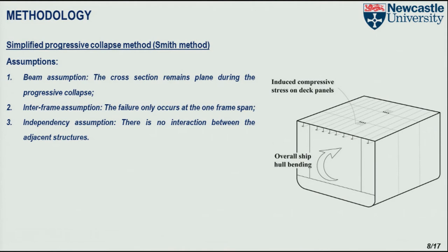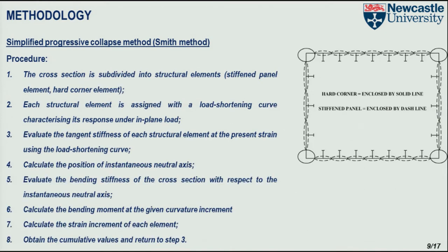Step one and step two are essentially preparation, and the actual calculation is done by repeating step three to step eight. We will first evaluate the tangent stiffness of each structural element at the present state using our load shortening curve. Essentially, we take the derivative of the load shortening curve, and the derivative of the load shortening curve is the tangent stiffness of that structural element. And we can then calculate the position of the instantaneous neutral axis of the cross section by using the tangent stiffness property of the elements.